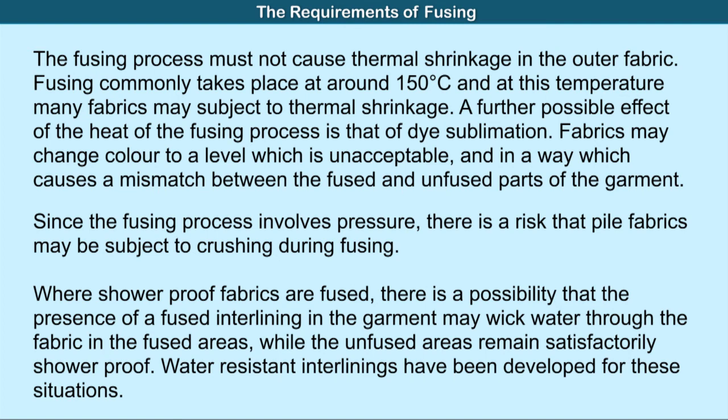Since the fusing process involves pressure, there is a risk that piled fabrics may be subject to crushing during fusing. Where showerproof fabrics are fused, there is a possibility that the presence of a fused interlining in the garment may wick water through the fabric in the fused area, while the unfused area remains satisfactorily showerproof. Water-resistant interlinings have been developed for these situations.